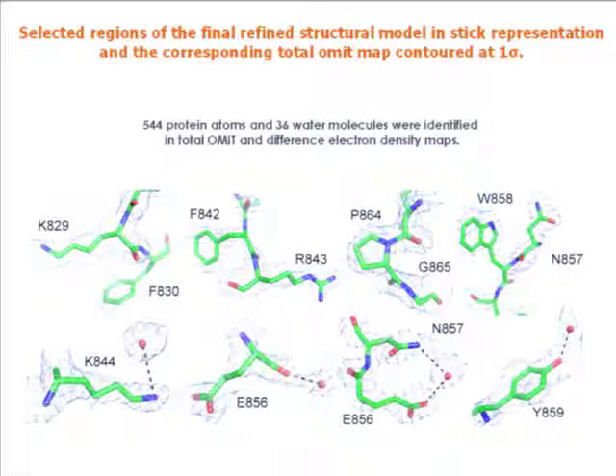Here you see parts of the total omit map at the final stages of analysis. We had 544 protein atoms in the asymmetric unit, and 36 water molecules were also located from omit maps and difference electron density. So protein people look more at the fit to the electron density rather than the data. And here you see at the final stages of analysis a few amino acids and how well they agree with different electron density maps. This is basically the end of the analysis when we have a reasonable model, stereochemically reasonable, the fit to the various density maps is quite satisfactory, and the fit to the data is quite satisfactory.